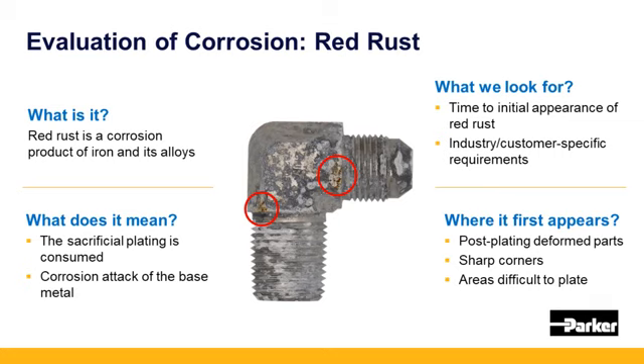Now let's look at red rust. No need to explain, everyone knows that's how iron and steel get oxidized. When we see the appearance of red rust, that means the sacrificial layer is already consumed, at least in that local area, and corrosion attack proceeds on the metal substrate. Over the test, there are a few things to look for. First is the time to the initial appearance of the red rust. On top of that, different customers may develop their own standards, such as some manufacturers using a certain percentage area of the product covered by red rust before a certain amount of time as their pass or fail criteria.